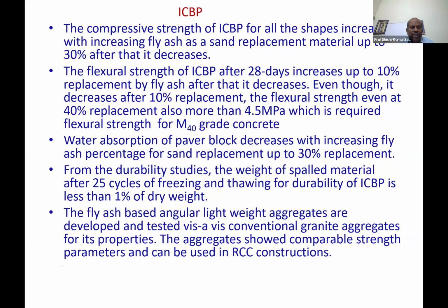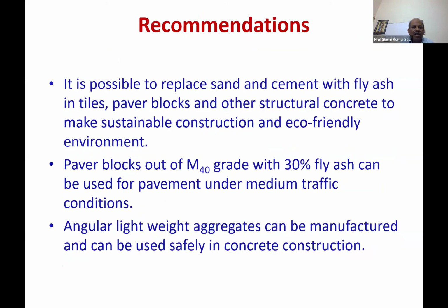From the durability studies, the weight of spalled material after 25 cycles of freezing and thawing is less than 1% of dry weight, which means its durability is good. The fly ash based angular lightweight aggregates are developed and tested vis-a-vis conventional granite aggregate for their properties. The aggregates show comparable strength parameters and can be used in RCC construction.